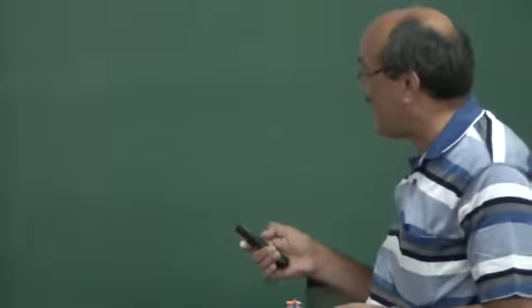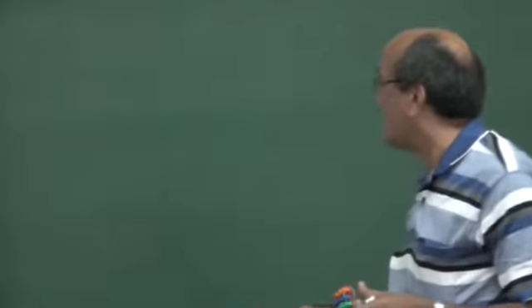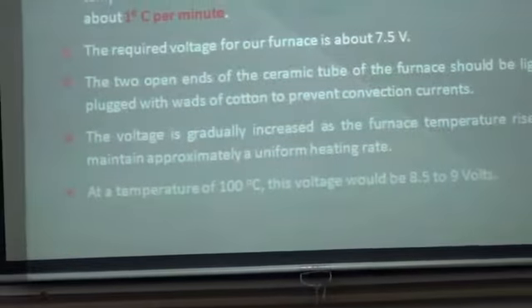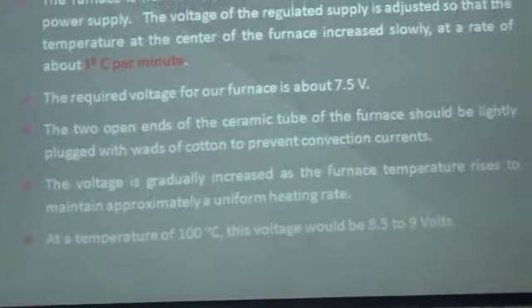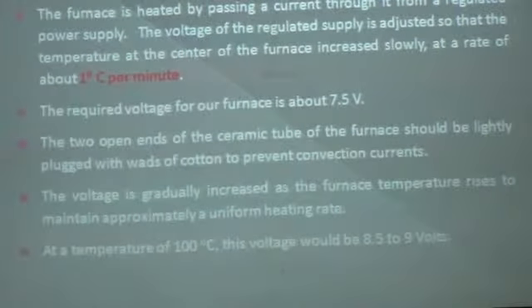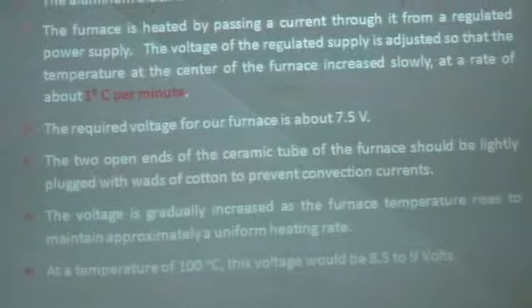So you have to regulate the temperature in such a way that you get a temperature rise of 1 degree centigrade every minute, 1 to 1.5 degree centigrade per minute. You have to begin with a voltage of around 7.5 volt, which you will find already there on the panel. When you switch on, you will see a voltage of 7 or 7.5 volt. You have to increase it; a voltage of 8.5 to 9 volt is required to get a temperature of 100 degree centigrade. You have to start from the room temperature, let us say 35 degree centigrade, raise the temperature by 10 degree centigrade and find out the voltage across the two leads.